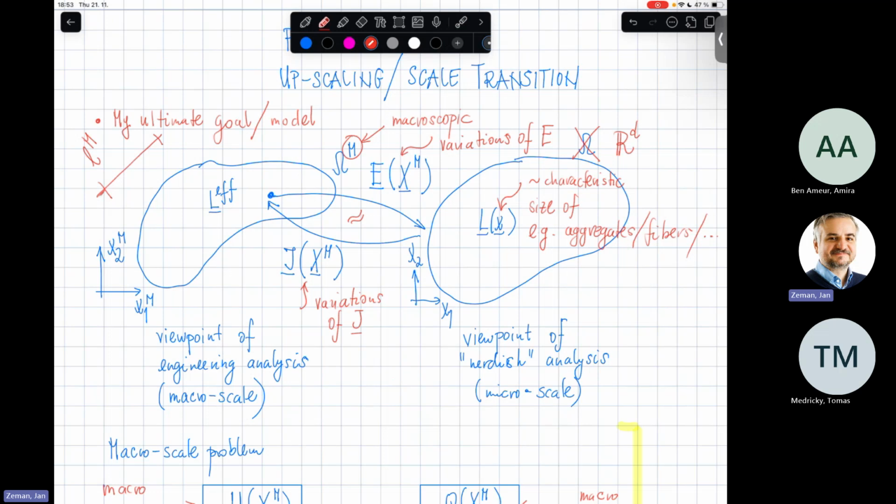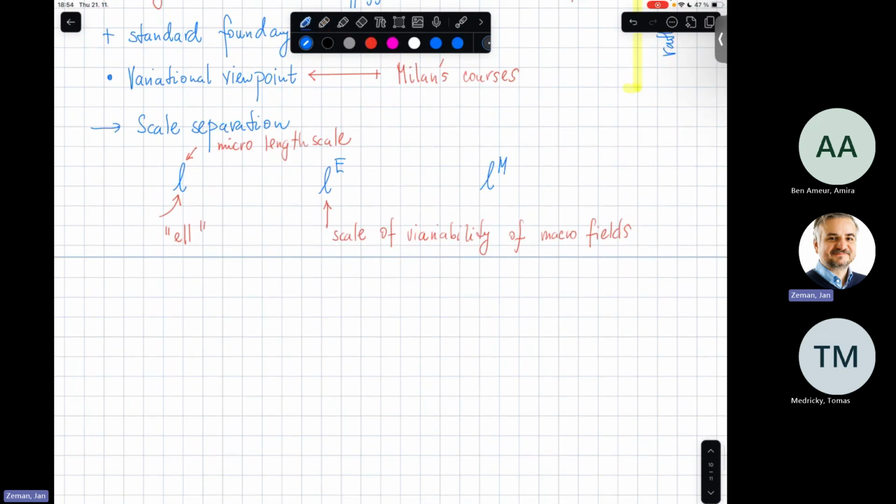And now, to have this model correct, and I hope now this argument is complete because I refined it several times, one thing which you need to make sure is that this L is substantially smaller than LE. So these two inequalities mean substantially smaller.